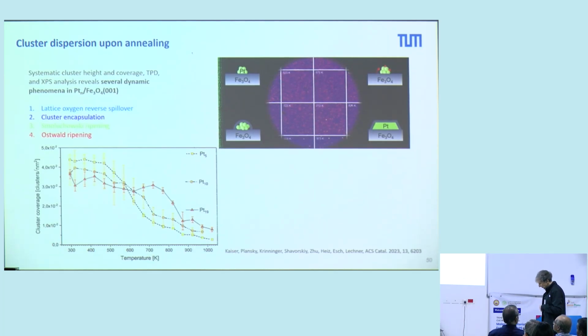Now what I would like to show you is that by using different techniques, TPD, XPS, and also STM, we will see that the clusters are stable at given temperatures, and then we have a reverse spillover of oxygen onto the cluster. And then if we increase the temperature even further, we have an encapsulation. That means we form a very tiny iron oxide over these platinum clusters. And then only at this stage, they start to migrate. We have Smoluchowski ripening, and at the later state, we have Ostwald ripening.